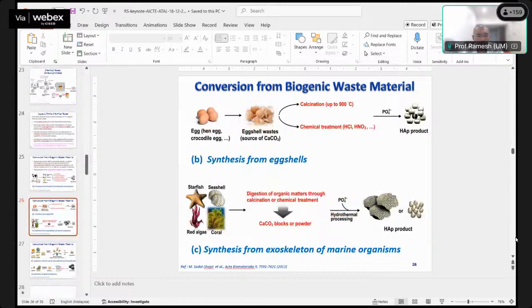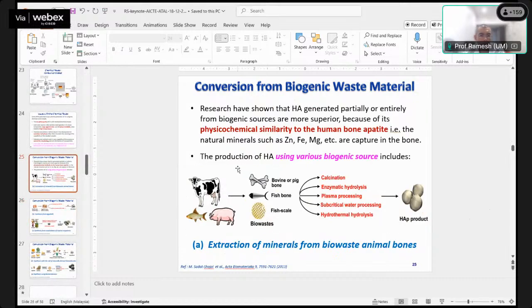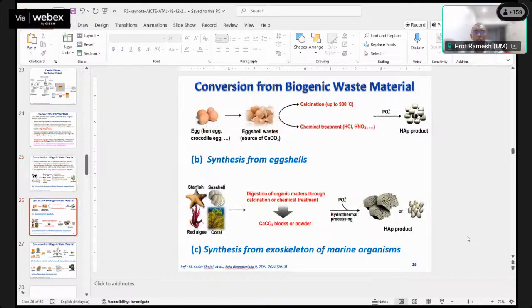Okay, so I've worked with bovine as well. I've not tried pig bones because, from research that has been done, it seems that the pig and chicken... I've tried chicken, but chicken bone is too soft. And the product that you obtain, the hydroxyapatite that you subsequently make out of the chicken bone, does not have very good mechanical properties. Fish bone, also the same. It can be a good calcium source, but the subsequent processing making it into hydroxyapatite, when you test the mechanical properties, it is not as good as using eggshell or bovine bone.